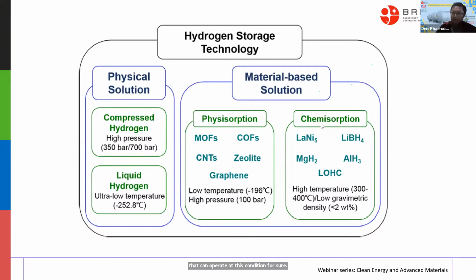And then this is for the commercial option like metal hydride, like lanthanum pentanickel, lithium borohydride, aluminum alanate, magnesium hydride, LOHC, etc. So this is the condition, usually about 300 to 400, and the low gravimetric density is less than 2 weight%. For the carbon itself, about 2 until 5 weight%, if I'm not wrong.